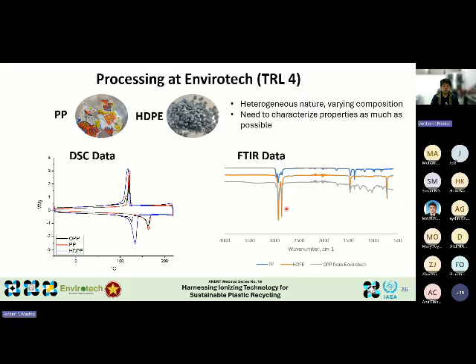One of the most notable observations we made at this stage of the project was that the polypropylene, the OPP that we sourced from Envirotech, was not completely pure. This is expected, but the result we've obtained is quite telling. It showed measurable contamination by HDPE. At this point, we are investigating the possible reasons for this. It may be that the contamination comes from the equipment used during collection or processing, or perhaps it reflects something inherent in the raw materials used.